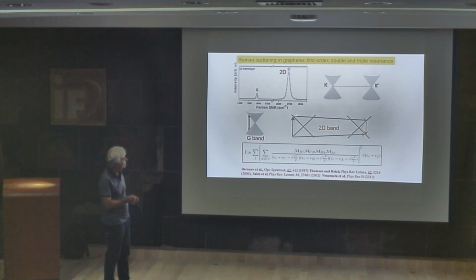The electron is scattered from this point to another point by emitting a phonon with a large wave vector. The hole is scattered from this point to that point, and here there is the electron-hole recombination. You see that this is a fourth order process because I have 4 arrows here. It's a higher order process, but it was realized that we can have in the denominator 3 terms, and those 3 terms can be resonant simultaneously. That's why we get a very strong peak.